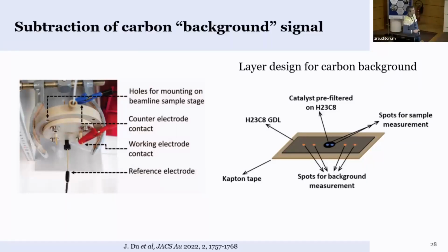In the ESRF design, basically by changing the incident angle, as said, you can choose if you are in the catalyst layer or back in the carbon layer and do the subtraction by this. So that's more convenient. One thing in both cases is that it's not exactly the same carbon, but that doesn't seem to matter so much, as long as you can subtract a signal from the degraded carbon.